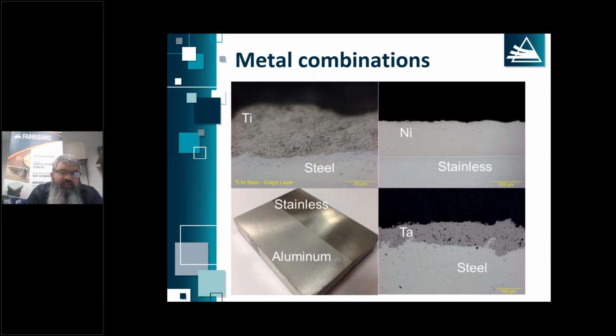A few more images here just to show you some of the dissimilar metal combinations that are possible. Titanium to steel seems like an odd one. That was actually for ice skates. Nickel to stainless for corrosion, tantalum to steel for corrosion, aluminum to stainless as a transition joint. We've actually arc welded to the stainless steel on one side and arc welded to the aluminum on the other to create a dissimilar metal transition.